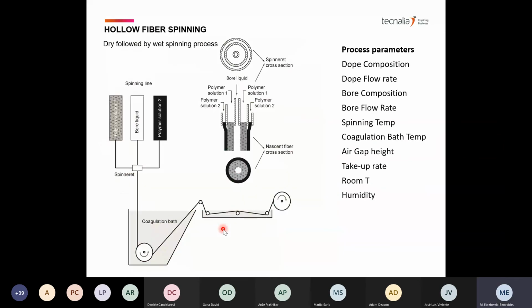Hollow fiber membranes are usually prepared by a dry-wet spinning process. In that process, a polymeric solution is extruded together with the bore fluid through a nozzle called a spinneret. During the residence time of the fiber in the air gap, some of the solvent is evaporated and the selective layer of the fiber is formed. Then the fiber enters the coagulation bath, where the substructure of the fiber is formed, and during the spinning process, the fiber is continuously collected on the drum.